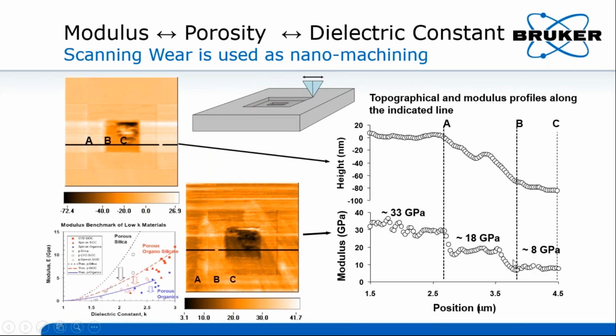The results show that the low-k film has higher stiffness and thus a higher dielectric constant on the top surface, on the original surface. And the depth dependency is so significant in the thickness direction.